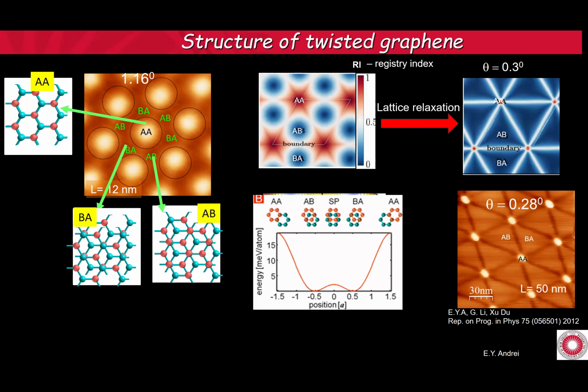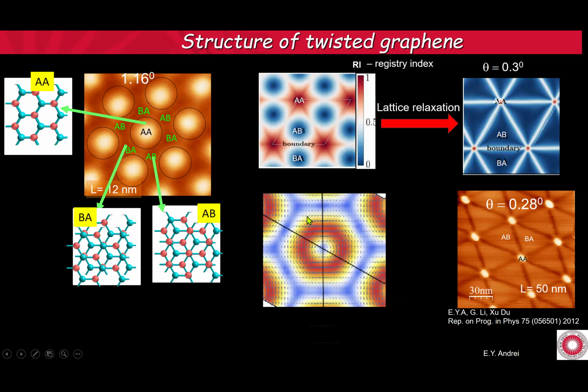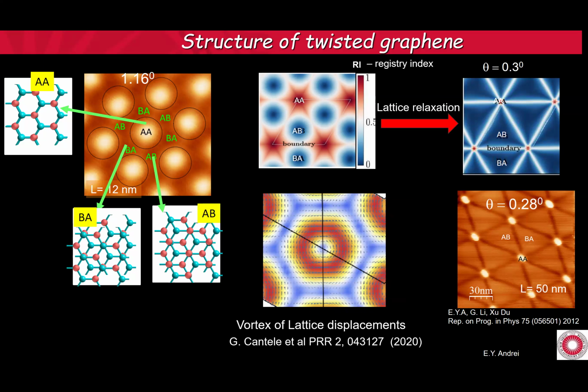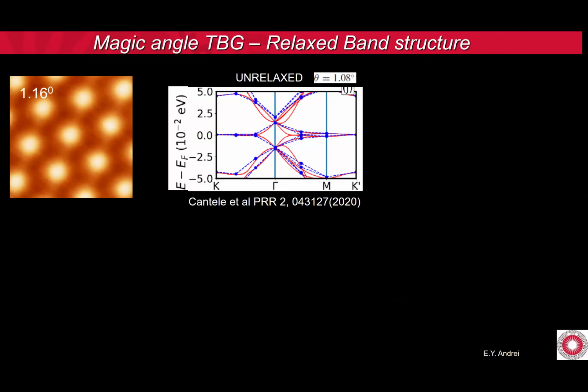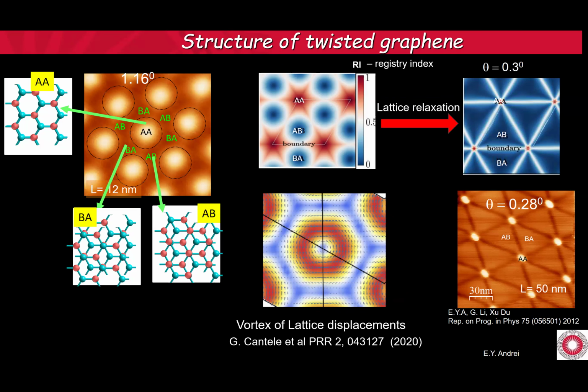Experimentally, we see the same thing. This is 0.28 degrees. These are the AA regions, AB and BA, and these are the saddle points here. What's interesting to see also is that this relaxation involves a vortex. I don't know if you can see these little arrows, but the atoms are shifting clockwise a little bit in the top layer and anti-clockwise in the bottom layer. So there is an actual vortex of lattice displacement that is created.